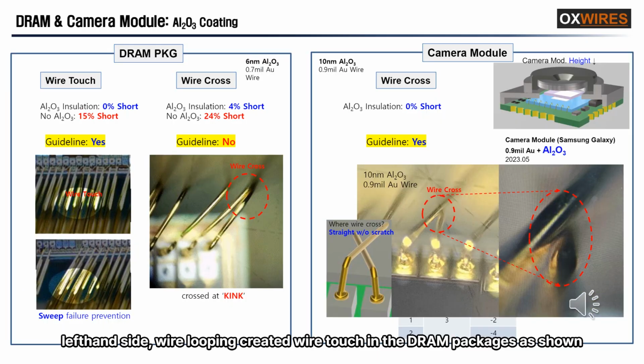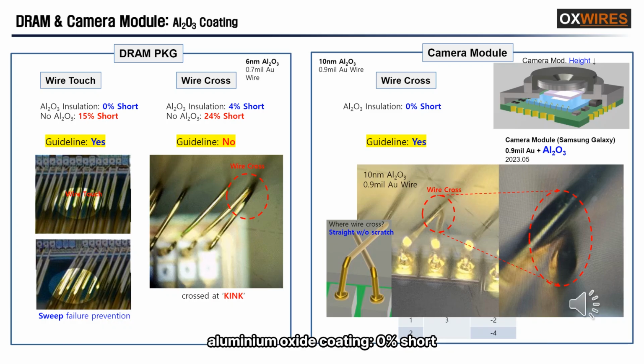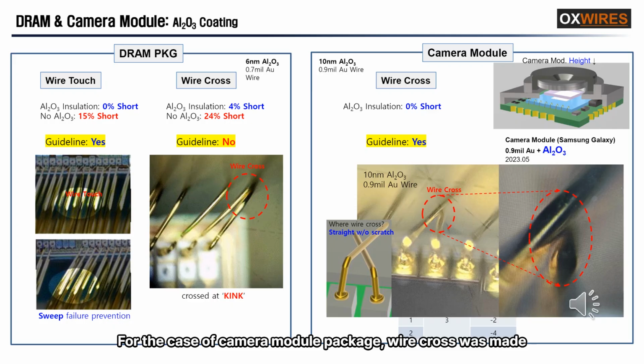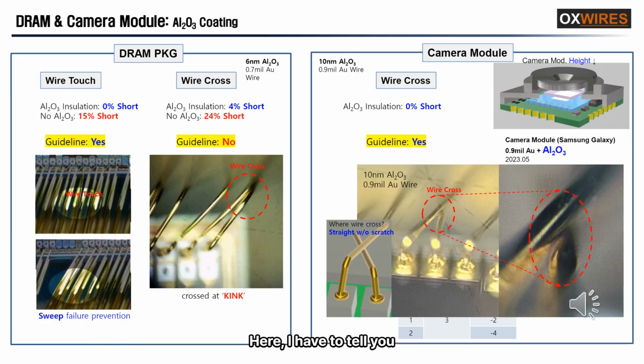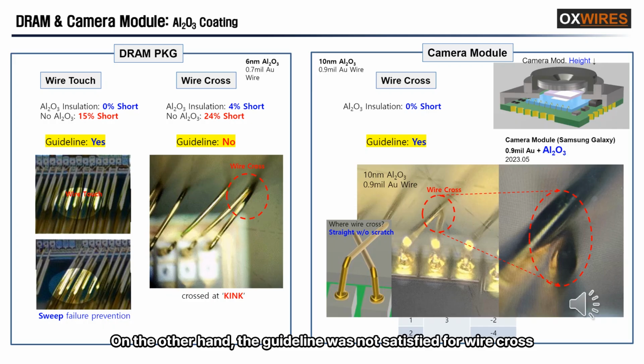Left-hand side. Wire looping created wire touch in the DRAM packages as shown. Aluminium oxide coating, 0% short. Conventional wire, no aluminium oxide coating, 15% short. Next, wire cross case. Aluminium oxide coating, 4% short. Conventional wire, 24% short. For the case of camera module package, wire cross was made. 0% short occurred for aluminium oxide coated bond wires. Here, I have to tell you, the guideline was satisfied for wire touch testing. On the other hand, the guideline was not satisfied for wire cross. On the next slide, I am gonna explain about the guideline.